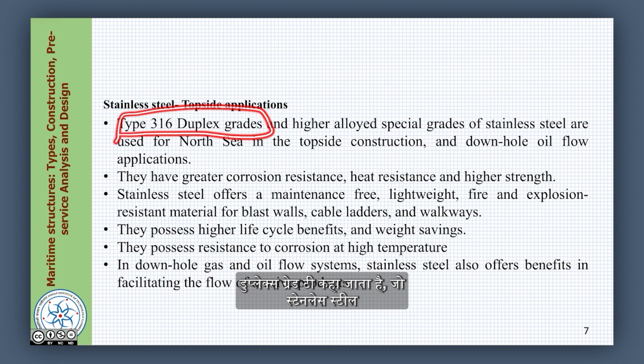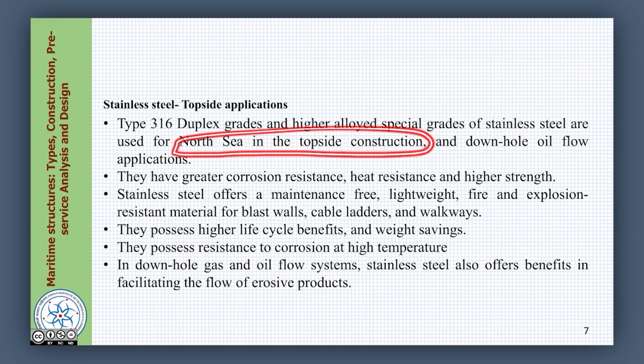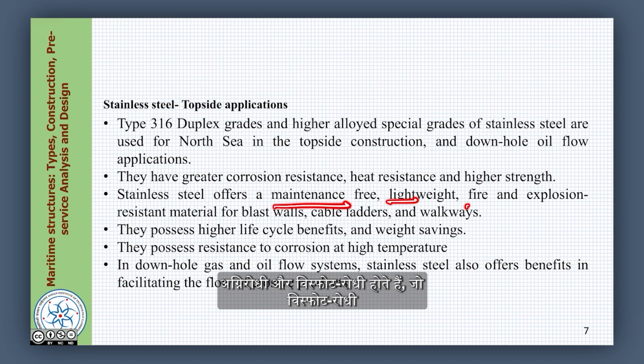One specific grade of stainless steel, called type 316 duplex grade steel, which is a higher alloyed special grade of stainless steel, is used where there was proof of its use in the North Sea in topside construction and downhole oil flow applications. There are very specific reasons why they have been used in these applications. They have very good corrosion resistance, very high strength and very good heat resistance. Stainless steel, friends, offers maintenance free, lightweight, fire and explosion resistance, which is very good for blast walls, cable ladders and walkways, because these structural members are more prone to blast, fire and explosion loading.